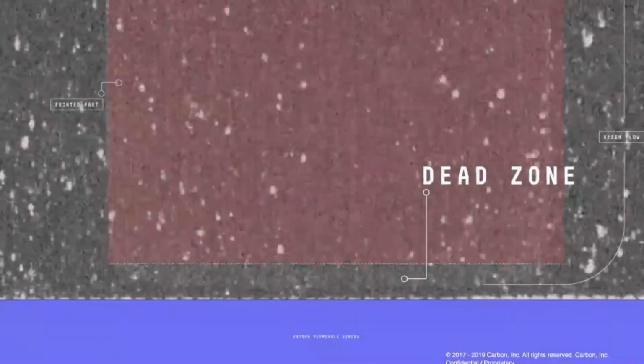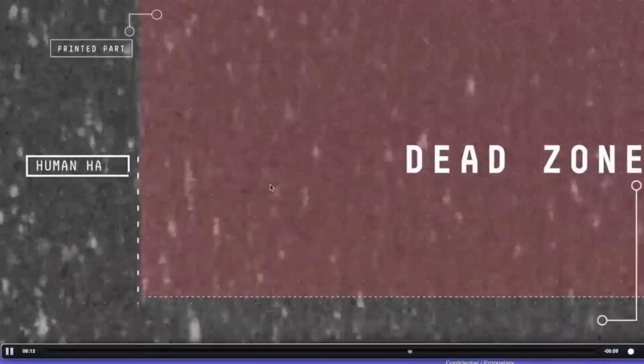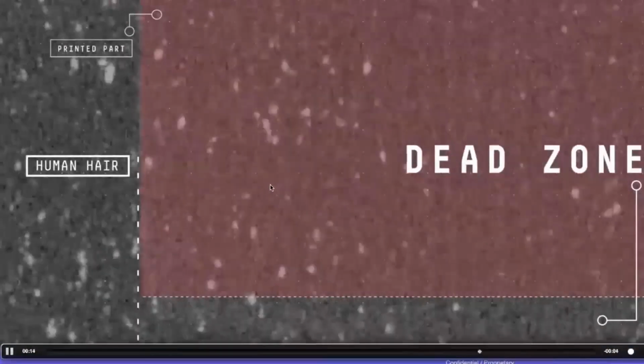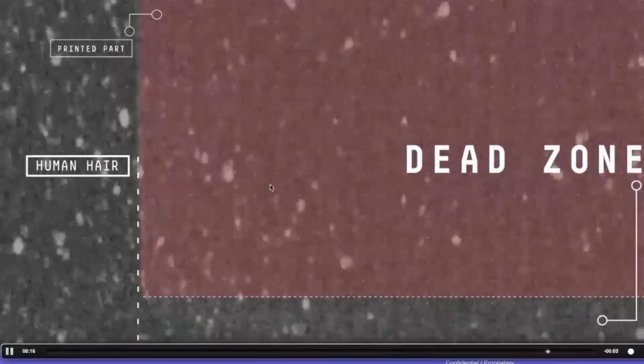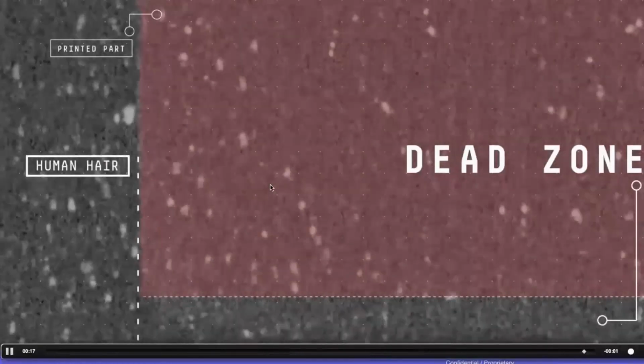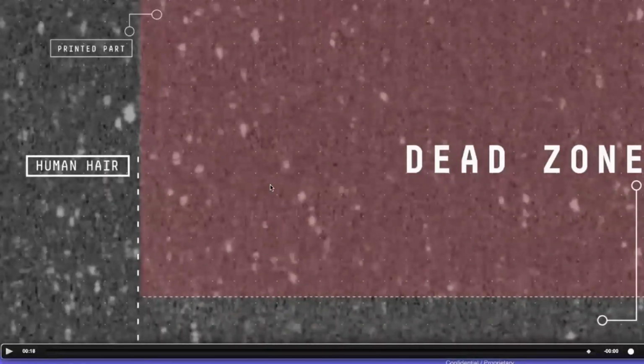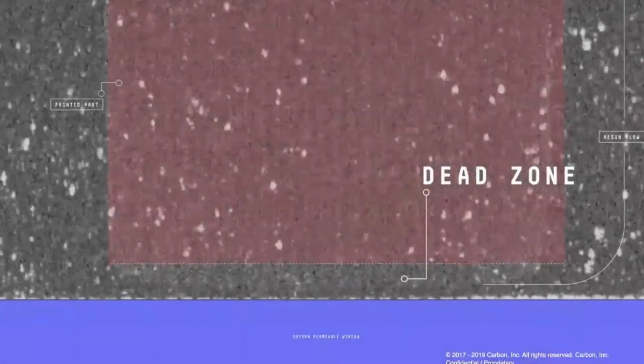And this is an actual image of a build surface. This is something called optical coherence tomography. It's a really powerful tool to allow you to see what's happening. But the part is bonded to the platform and gets pulled up. And as it gets pulled up, what you can see is that there's a reservoir, or a channel, that's uncured underneath the part that allows a river of resin to come in underneath the part. And that river of resin becomes a conduit for resin renewal without having to delaminate it off the surface. And so it's a breakthrough.